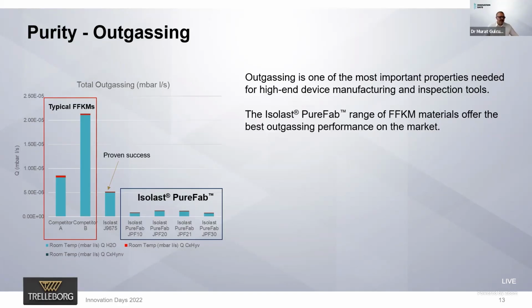So you can see again on the screen the outgassing performance. So this is RGA, residual gas analysis. By the way, partial pressures were measured. You can see two competitive materials are quite high, and previously we had Isolast J9675 material, which has been used in very extreme locations where low outgassing is needed. It has been used, but even our new Isolast PureFab range has even better performance than our best material which we had in the past.